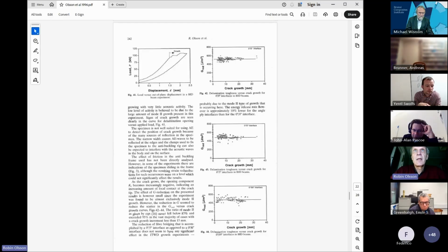So I think that indicates that the initiation values you get from, for example, a conventional ENF test are not very relevant for predicting delamination growth in impact testing. The values you get, 600, 700, 800, are far too high. You should actually look at values for this specific material around 500 joules per square meter. If it would be possible to do a mode 3 test, I think you may find similar things. But of course, in most cases, you will just get migration.